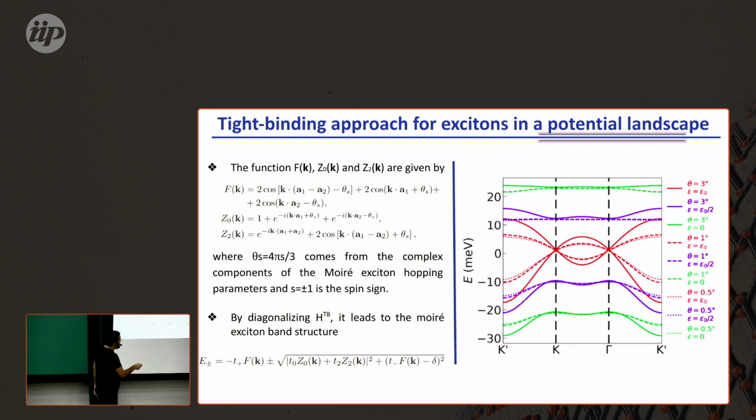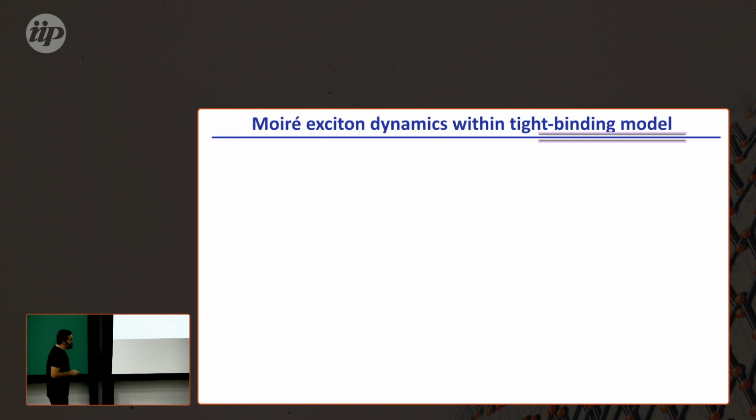And moreover, as you see in the dotted, dashed, and solid lines, by increasing the twist angle, you modify the group velocity. And if you look carefully around here, the crossing point, the gamma point, you see that the certain iso-energy contour is asymmetric.